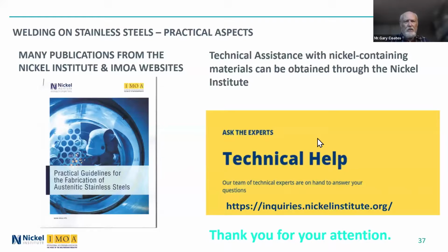If it were me facing this, I would actually do a metallurgical examination to determine exactly where the fissures or cracks are. Sometimes you can see things in LPT that are not serious, and other times they go deeper and are serious. So you'd like to see exactly what is happening there. My first opinion for that particular question is I don't see anything wrong with what you're doing, but you need to do a metallographic examination to actually see where the cracks are starting. It may be a contamination issue. The nickel alloys are very sensitive to contamination, but you really have to look for that.